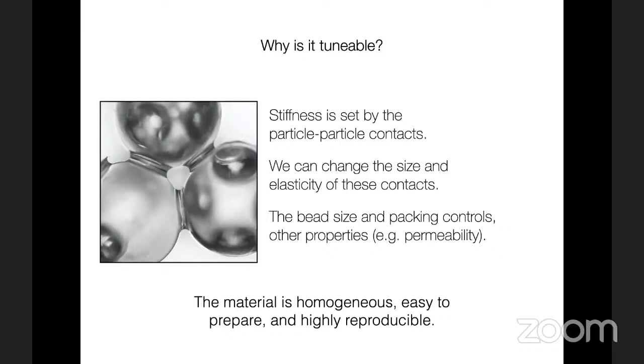So the main things we have to control are the size of the bridges by adding more or less polymer, the cross-linking of the bridges, which changes the elasticity of it. We can also play with the bead size and to a much lesser degree the packing. It's really hard to make any packing with this that's not something close to random close packed, something in the high 50s, low 60%. And the material has the benefit of being relatively homogeneous, easy to prepare, and very reproducible.